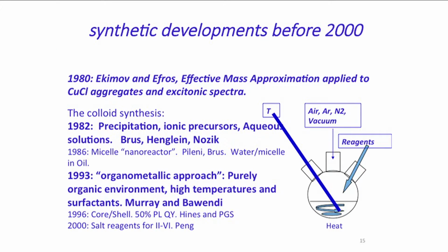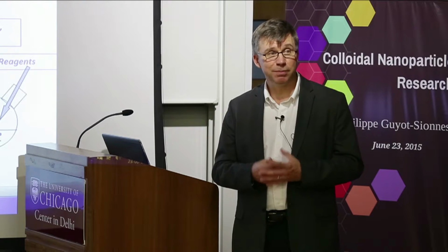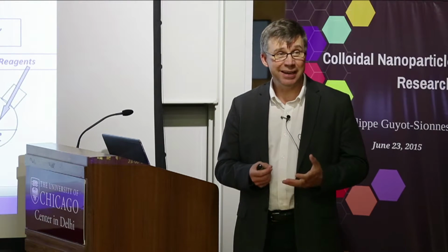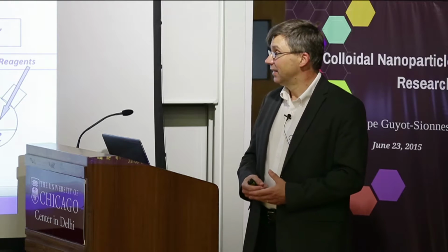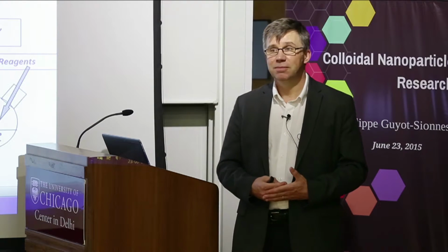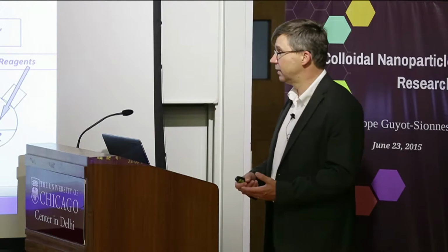In 1996, we introduced this core-shell idea to passivate the surface with a material that had a chance to be epitaxially registered to the lattice, and that led to robust and much enhanced luminescence. And probably the most important development in this area was then the introduction of salt reagents by Xiaogang Peng. That was important because it made it a lot easier for a lot of people to start working in this field. If you had to work with dimethyl cadmium, which is this pyrophoric thing that when you take it out in air, it will spontaneously burst in flame, it's a barrier. But if you can work with a salt of cadmium, then it's a lot easier.